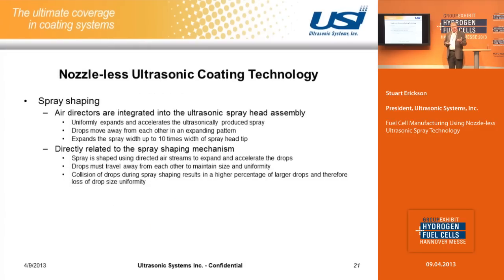So once you form the spray with ultrasonic energy, you need to actually shape it and give it some velocity, because the spray by itself is very soft. It doesn't really do very much for you. If you were to see it spray, it would drift with every little air current. So what we need to do is shape the spray, and we need to accelerate the drops. You don't need to accelerate them very much, but you need to accelerate them so that they have some shape. So what we do is we take that spray and we expand the drops. So all the drops are moving away from each other from the spray head, so they don't collide back with each other and get bigger. They maintain the size that they were produced ultrasonically, because we're expanding the spray with our air director. And typically we can expand the spray up to 10 times the width of the spray tip.